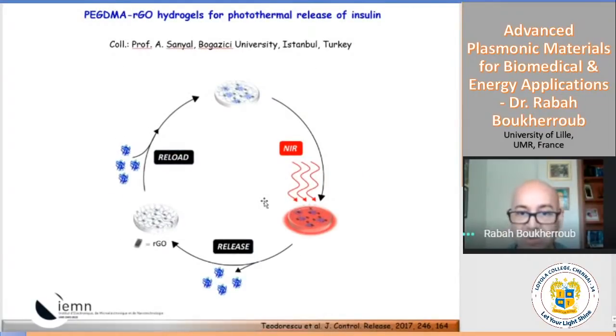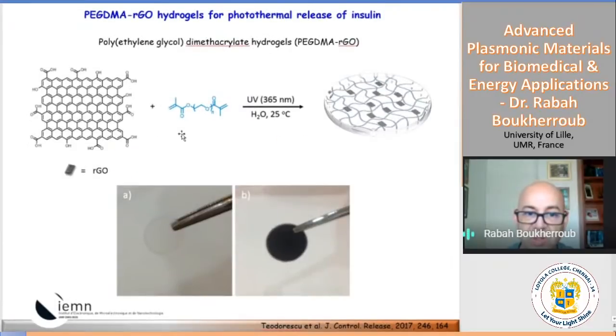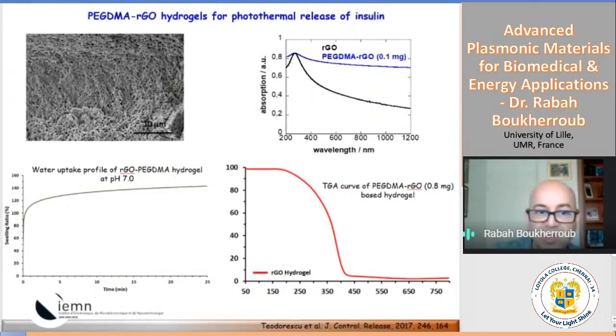So to do that, it's a collaboration with a colleague from Turkey. We made a composite material of polymer with graphene. It's a very easy way of doing it. You just polymerize dimethacrylate with graphene, using UV, and you see on the left side, when you don't have graphene, you have a very transparent composite thick film. When you have graphene, you have something completely dark and black because of the presence of graphene. It absorbs light.